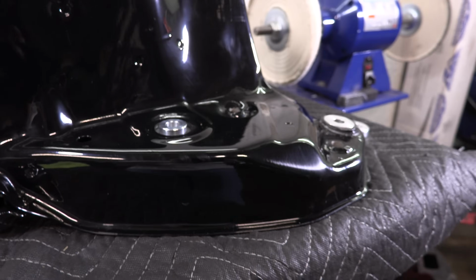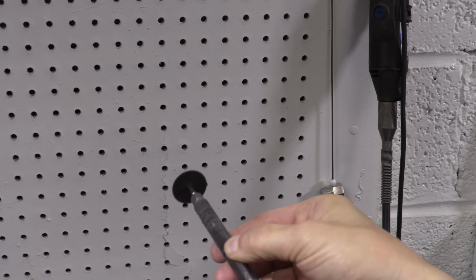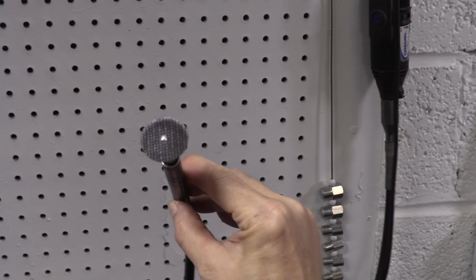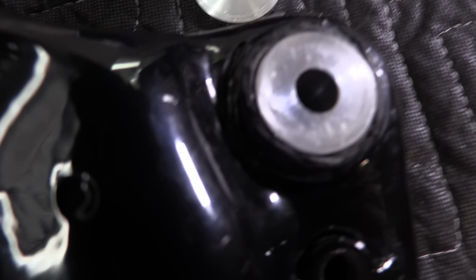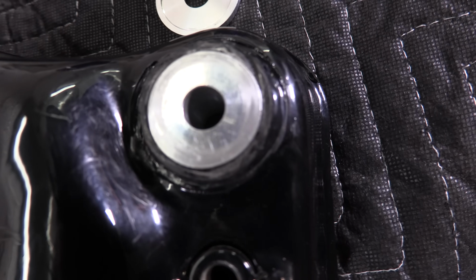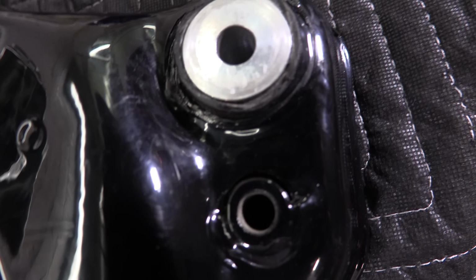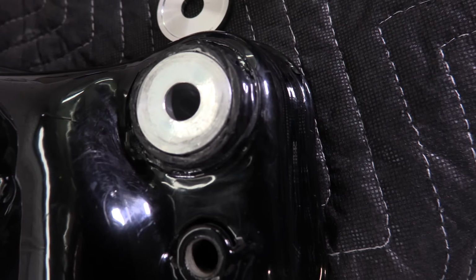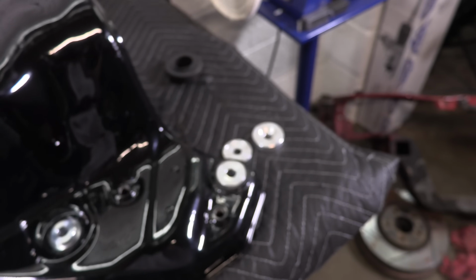So I went to the bench and I used a cutoff wheel with a Dremel around the inside edge of the boss to open it back up again so I could mash it through the rest of the way. The outside of the bushing boss turned out far worse than the installation itself because of how much force had to be applied to both discover the problem and to fix it. But what do you expect from 20 tons of force on a press?